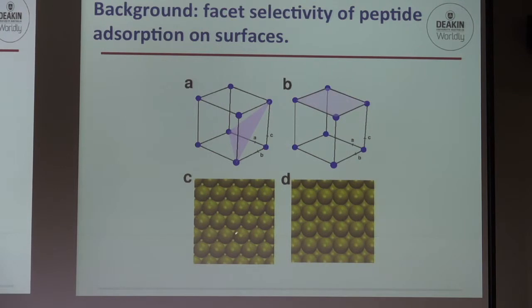On the left, what I'm showing you is the 111 facet, where I take a cut through that 111 plane there. And on the right, what I'm showing you is the 100 facet, which I'm taking a cut through the 100 plane. And they show a very different arrangement of the atoms. So this is for gold. And here you can see a sort of hexagonal arrangement of the atoms, and here it's more like a square arrangement. And you might think, well, what difference does this really make? Because it's quite subtle, but it can make a really big difference, actually, in terms of what peptide sequences want to stick onto these things.